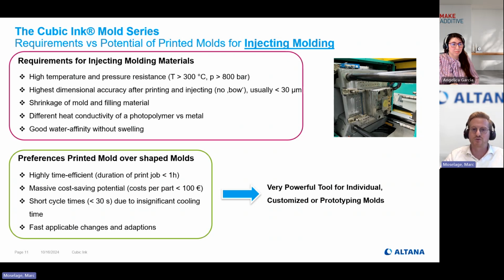It is not allowed to crack and shouldn't bow either. If it bends, that is also not tolerable. For injection molding, shrinkage is a big thing. Not only the shrinkage of the filling material, but also of the mold needs to be taken care of. And when you're doing that, and you did mold typically shaped metal, the heat conductivity versus a printed photopolymer is pretty much different. And again, removal by water needs a good water affinity, but swelling, the blooming of the material, definitely needs to be suppressed and minimized, as this can really destroy your final product.